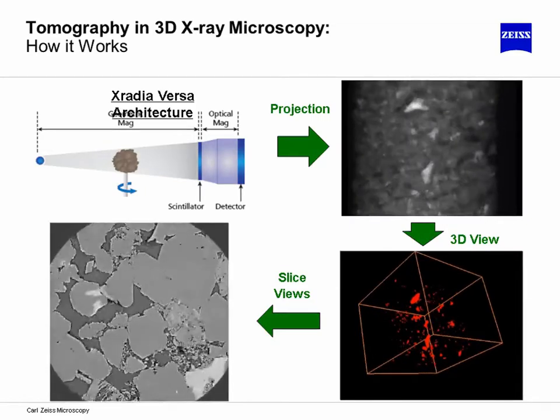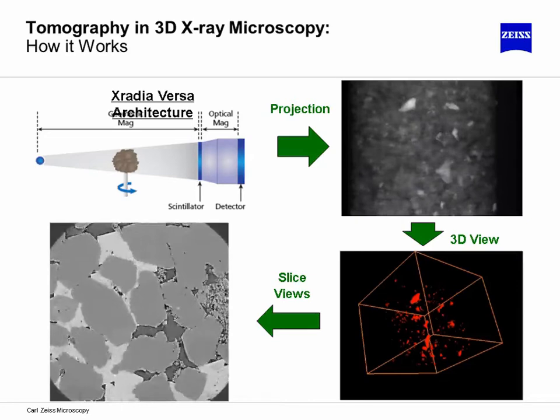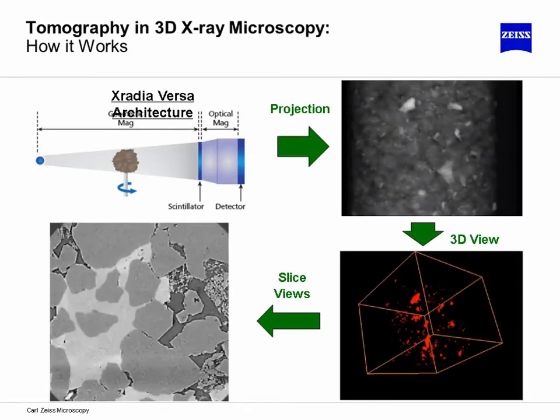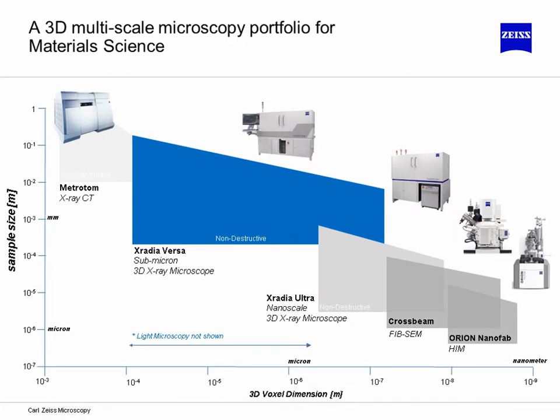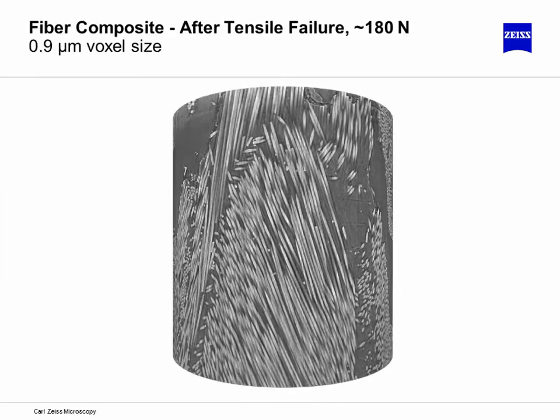Things like the density of the material are inherently inside of the data and can be extracted as well, although you're not given any direct compositional information from this. Spectroscopic techniques such as EDS or fluorescence would be more logically performed to obtain specific chemical information. The beauty of this technique is that you have that three-dimensional information non-destructively, and you can subsequently go back and perhaps deform or anneal that sample and look at its evolution.